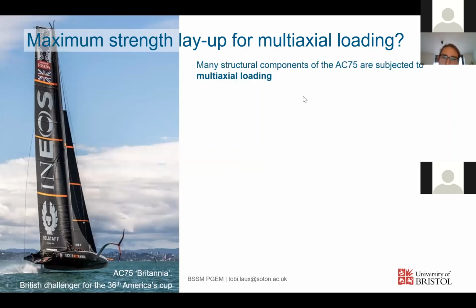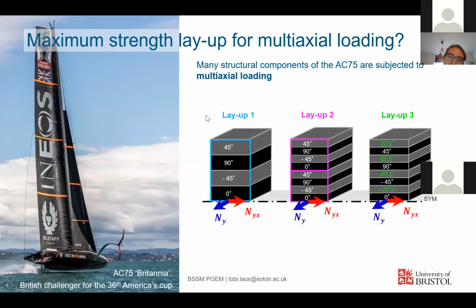As said, many structural components are multiaxially loaded. What they were curious about is what quasi-isotropic laminate gives them the maximum strength at minimum manufacturing cost, really. Typically, for their quasi-isotropic laminates, they use a stacking sequence with 0, -45, 90, 45 plies. They were in particular curious what happens if they have a smaller relative fiber orientation angle or pitch angle. So we added 22.5, -22.5, and 67.5 degree ply angles in the laminate, and we wanted to see what's stronger under what loading.